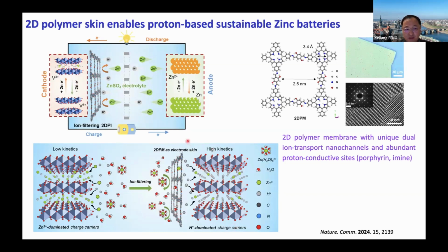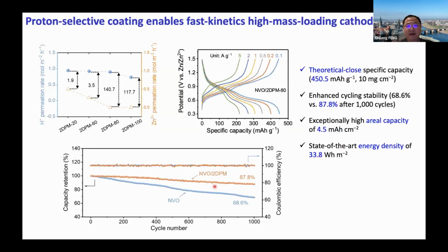So this shows the idea: we put the membrane protection on the metal oxide cathode, and we'd like to have the majority of proton ions for the intercalation. So we can increase the kinetics and also the durability of this device. And this just shows the membrane, where indeed we find that if we increase the thickness of the membrane from 20 nanometers to 80 nanometers, we can greatly enhance the selectivity of the proton ion over zinc ion.